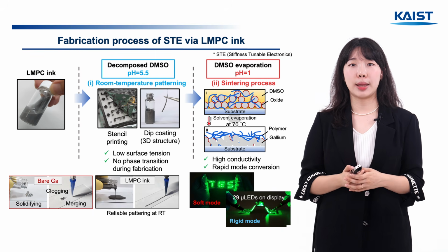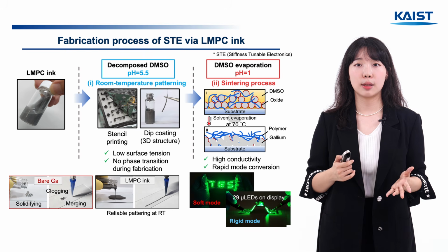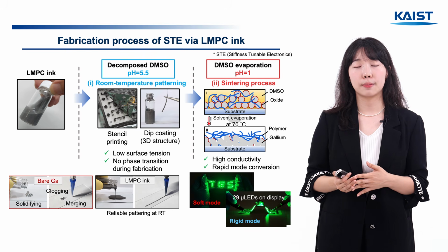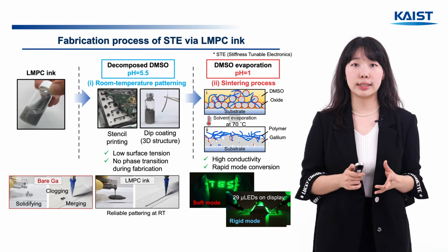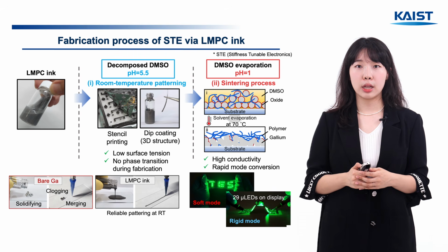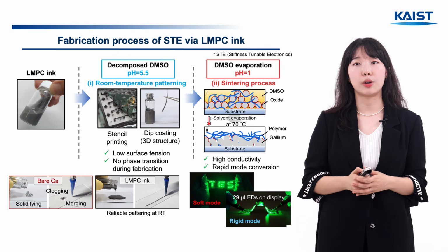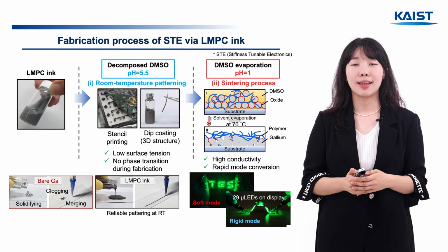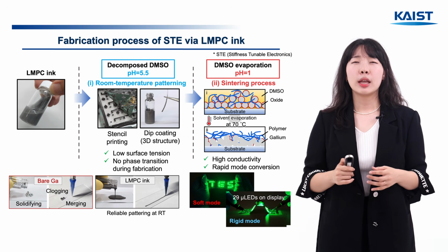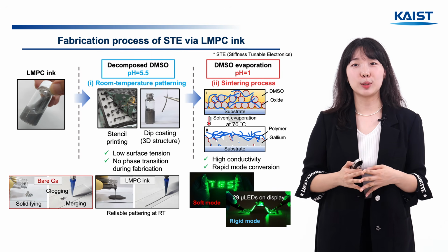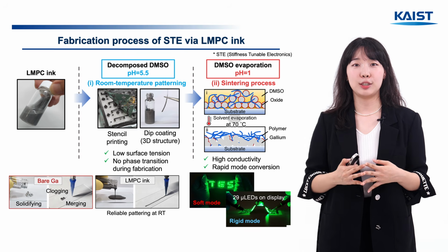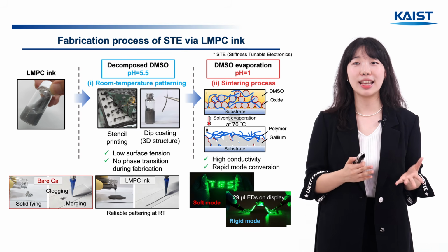Here's the process of making stiffness-tunable electronics by using our LMPC ink. First, in the printing stage, the ink is well dispersed, so it can be stencil printed or dip coated at room temperature. Then, during curing, the particles sinter, and the resulting stiffness-tunable devices show high electrical conductivity and also a fast switching speed.